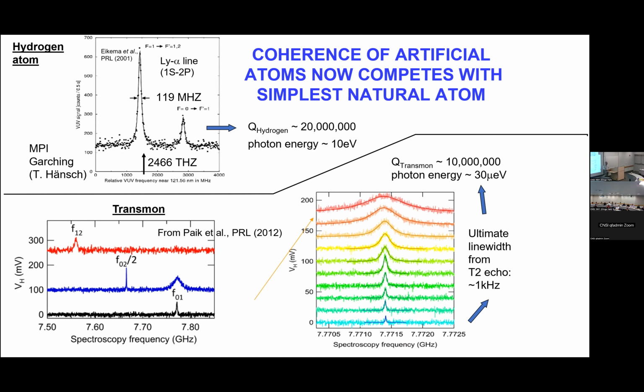So this is the real challenge in the field, how you can get over this 20 million. For error correction, if you want error correction to really develop its power, we can live with this 10 million and do interesting experiments that I don't have time to present, which show that quantum error correction is possible. But in order to fully develop it, we need to go above this 10 million. We have to go over this 20 million, maybe by a factor of 2. So that's where we are.